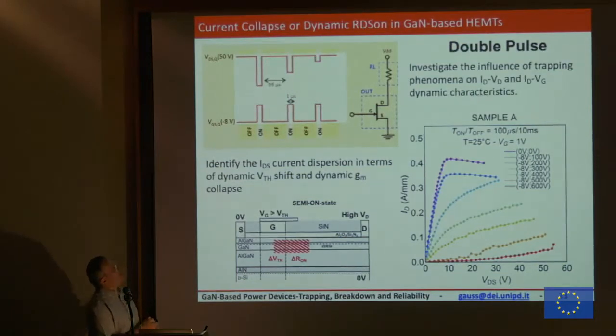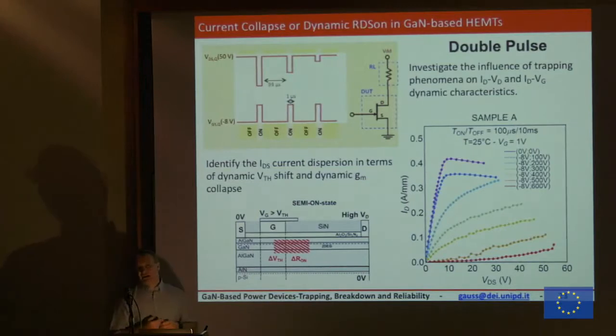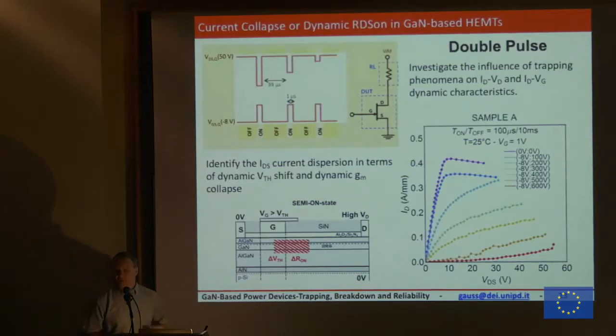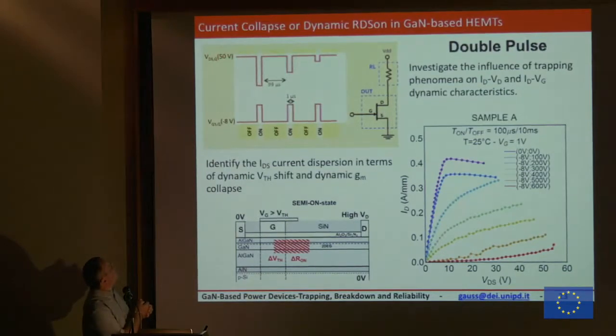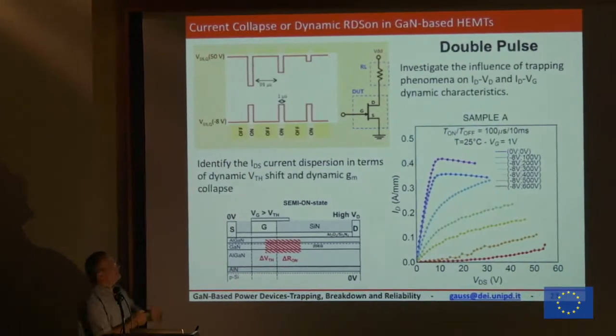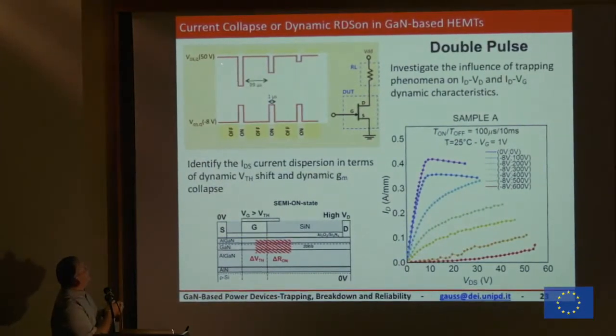And we do what we call a double pulse. If you go in the field of these devices, you will always hear about double pulse measurement. What is it? You take your device and you pulse the gate and drain simultaneously, starting from a condition that we call off condition. So you see the VGS is low, so it is below the threshold voltage, so no current. And we have a high VDS. This we plot to 50, but this can be 100, 600, whatever you want. In this condition, the device is off, and then we turn on immediately. And then we measure the current. And then we change the VDS and VGS, and we see what we have.